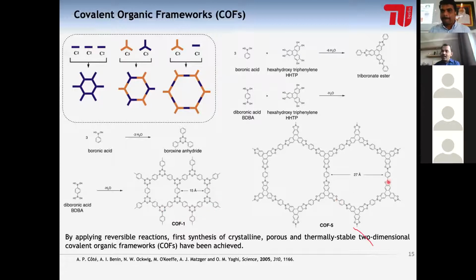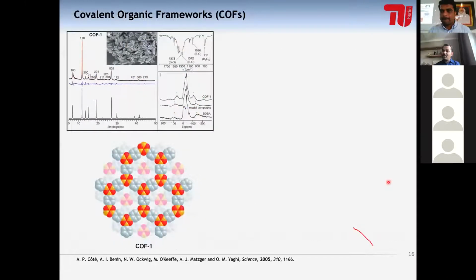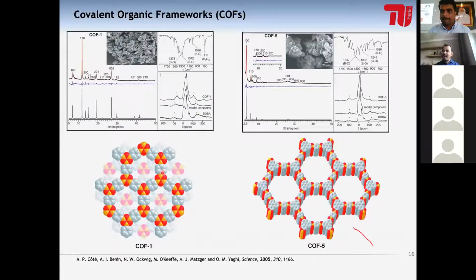And when it comes to the synthesis and structure of these materials, it is possible to detect the ultimate structure of these materials. For example, these are the PXRD, powder XRD patterns, where in the last case I showed that these materials are completely amorphous. But when you form the covalent organic framework, these materials have very high crystallinity, and now we exactly know what kind of pores and what kind of structure these materials have. We can simulate the structure using Materials Studio and determine the exact structure of this material.